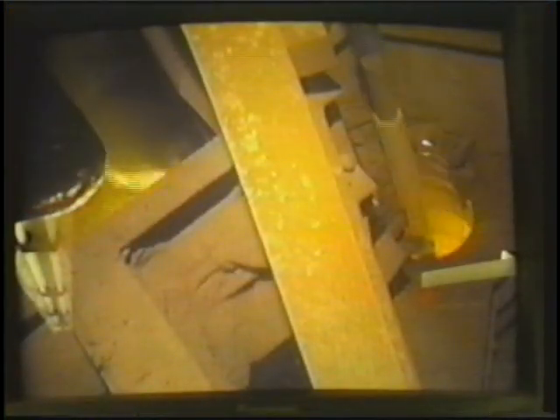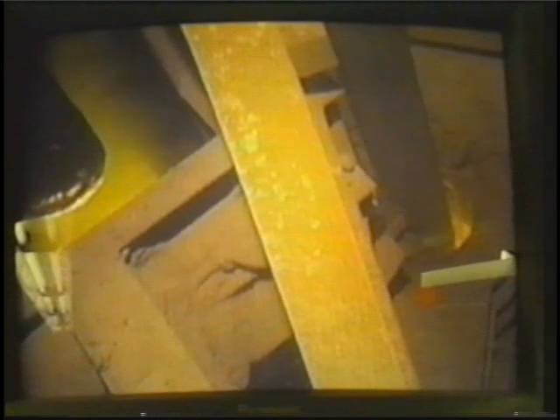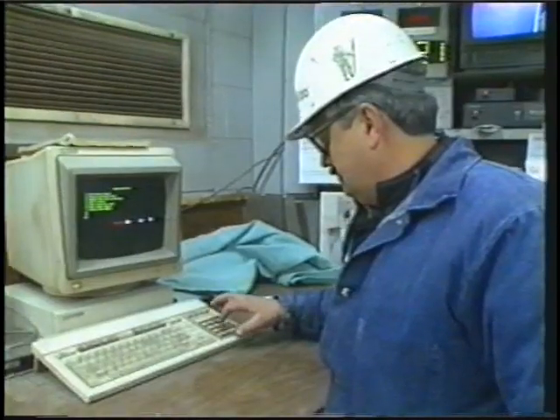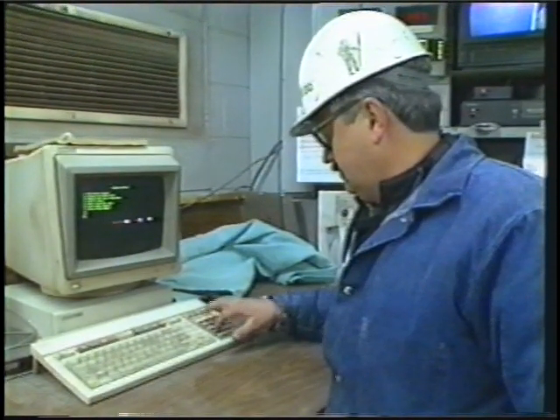A sublance is used to permit the operators to measure the temperature and chemistry of the molten metal, approximately 85% into the blow. Corrections can be made at this time to prevent reblows. The use of the sublance results in better alloy recovery, improved cleanliness, and reduced refractory costs.